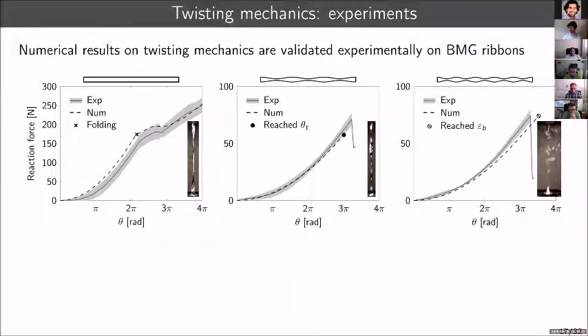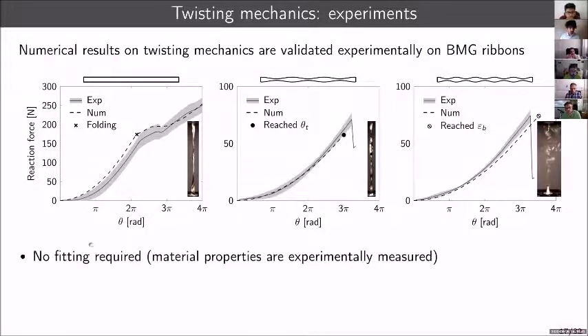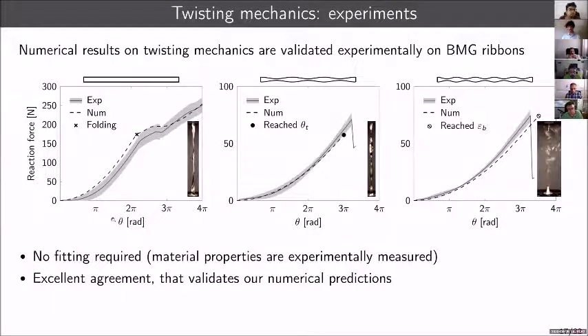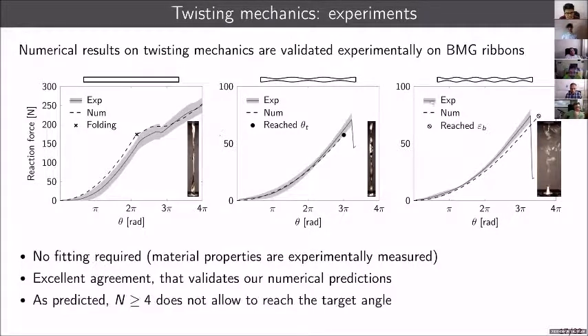Okay, so for these properties, we tried to compare numerics and experiments. What you see over here is the plot of the reaction force, because that's what we can measure experimentally. So the reaction axial force in response to twisting as a function of the applied angle. And what you can see is that there is no fitting required because we actually measured our material parameters independently. Despite that, there is excellent agreement between numerics and experiments, which tells us that at least we think we did a good job with those simulations. And in particular, here, the gray curves are the experiments with the standard deviation, and the dashed curves are the numerics. As predicted, for the experiments, if the number of necks is greater than or equal to four, then you have breaking before reaching the target angle.